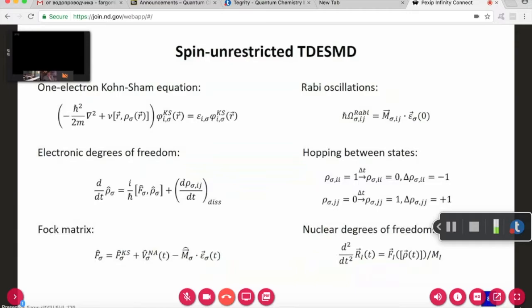And based on Rabi's theory, the Rabi frequency is related to the transition dipole and the intensity of the electrical field. So the propagation of the degree of freedom can be modeled by Rabi oscillations with hops between different states, and these hops can lead to a stepwise change of orbital occupation. So through these equations, we can get the updated density, the total density of electrons, and with the new density, we can update the interatomic forces, and with new forces, we can update the position of ions. Next slide.